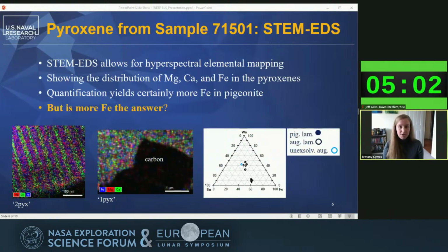Okay, so let's take a look now at the composition. We next use the STEM's EDS detector to collect X-rays from these regions, from which we can reconstruct elemental maps. You can see here very nicely domains of augite and pigeonite based on segregation of the metal cations, magnesium, calcium, and iron. We also collected on the adjacent unexsolved augite crystal. We can also quantify these data, which yielded these nominal compositions plotted here in this ternary diagram. And you can see, indeed, the pigeonite lamellae have more iron than the augite. So was more iron the answer to our nanoparticle mystery?